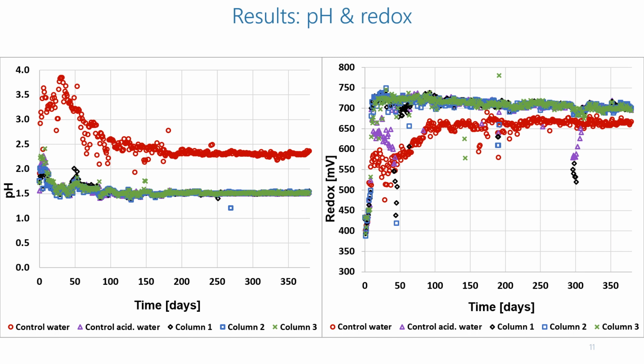pH and redox potential results show signs of microbial activity in the control column irrigated with deionized water, indicating a strong acid-forming potential of the discards under natural weathering conditions. Results also show a steady rate of leaching in all other column configurations.